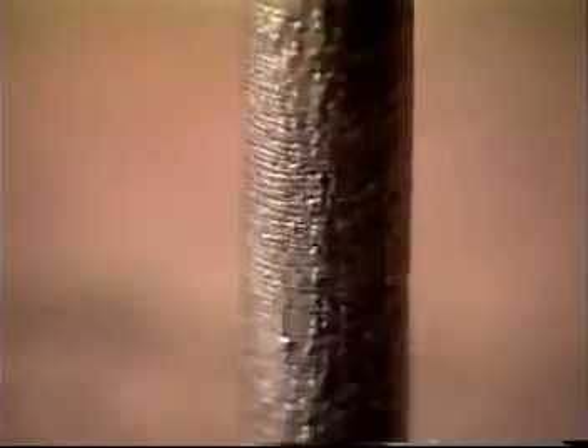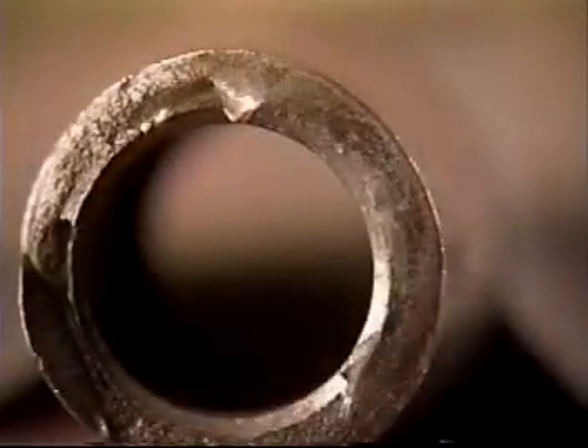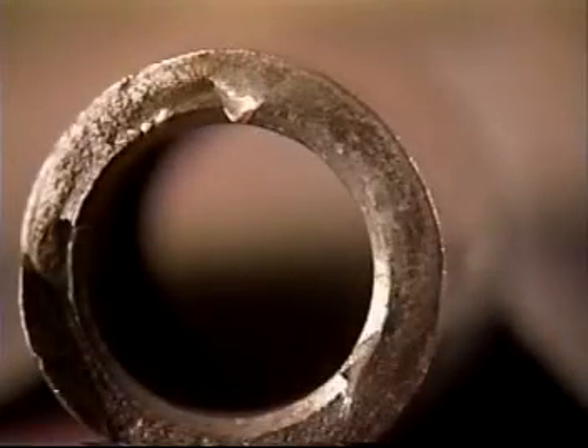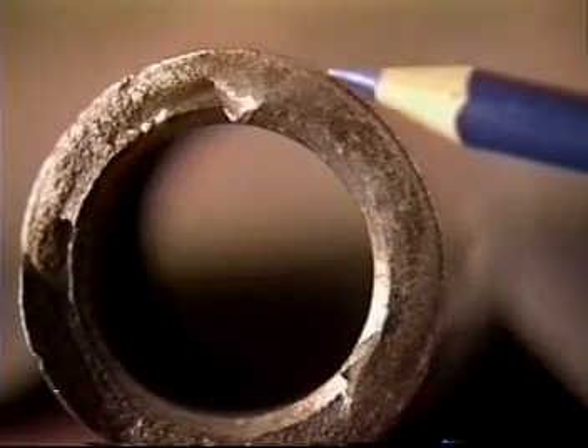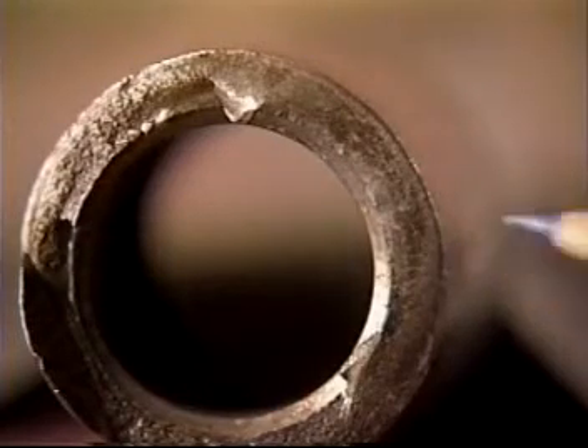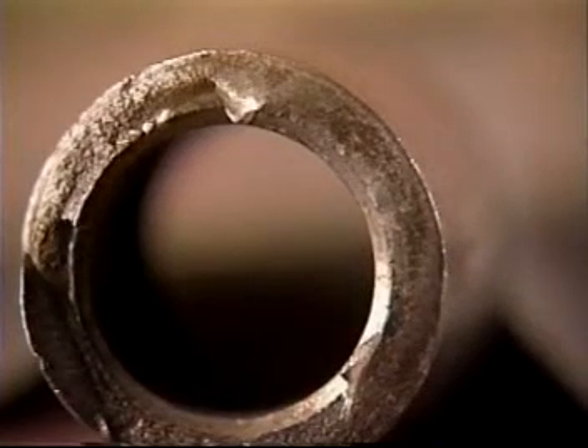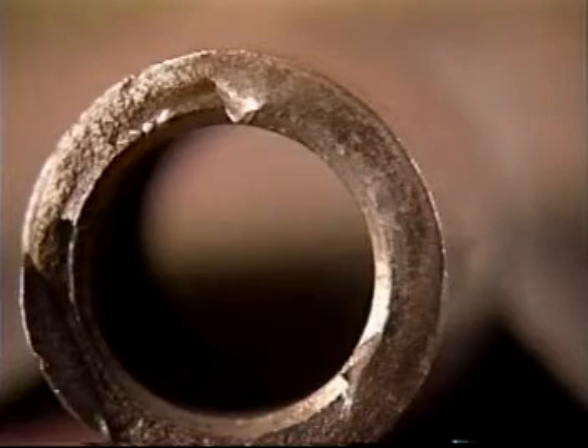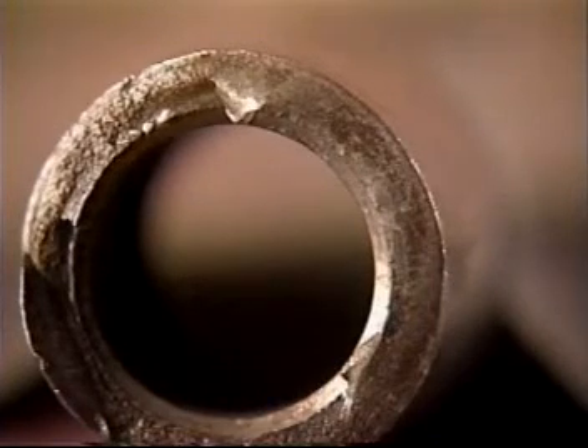Overloaded rods show distinctive stress cracking. These stress cracks will be very fine, extend all the way around the rod, and over the entire length of the rod. This pattern will even include the wrench squares. Overloaded couplings will fail in a 50-50 fashion. The break face will exhibit a small fatigue area, and the ratchet marks will initiate at the OD of the coupling. This is a common break for high-strength rods with 7/8" slim hole spray metal couplings.